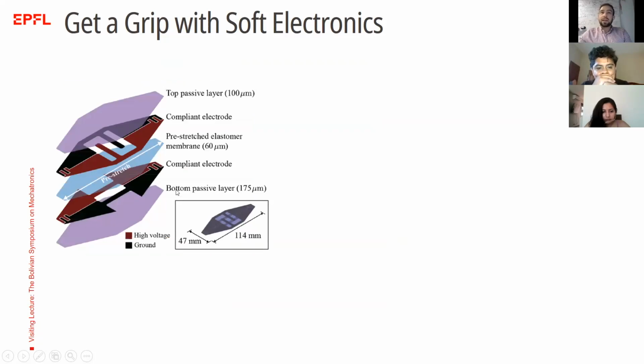Okay, what is the structure behind it? Actually, it's a layer-by-layer structure where we have two passive layers made out of silicone with a thickness of 100 micron. Inside we have two electrode layers made out of conductive silicone. Usually, to make silicone conductive, we just mix conductive particles with the silicone, then a blade casts it onto the silicone layers, and then these layers are put in an oven to be cured on each other.